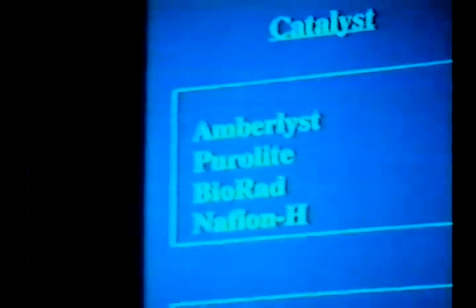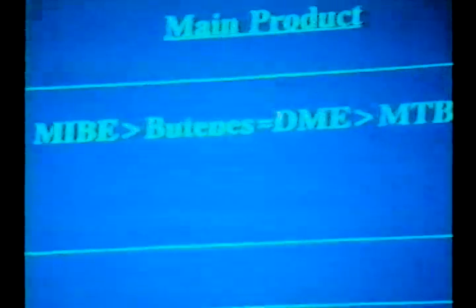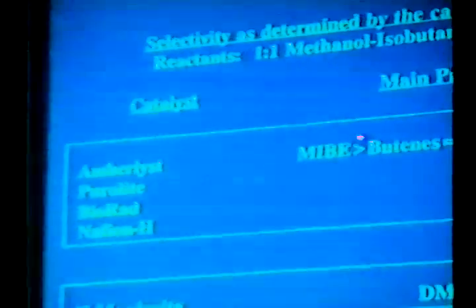The energy profile has been measured for these reactions. If we start with methanol and isobutanol, we can go to methanol and isobutene. We can also synthesize MIBE and water, either by bypassing to MTBE by the reaction of methanol and isobutene, or by direct isomerization, we can get to either of these two products. These are thermodynamic energies, which are very close to each other. These are kinetic activation energies, which really control the selectivity of these reactions.